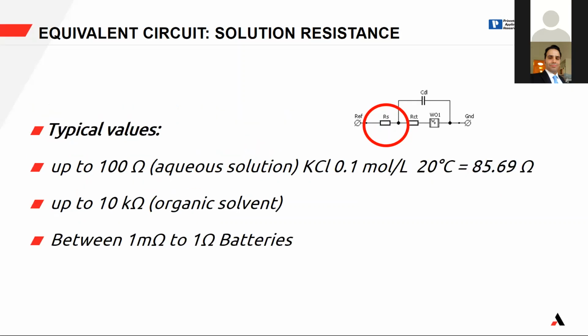The value: normally, if we are in aqueous solution, we are talking about around 100 ohms. I give you a comparison: KCl at 0.1 molar at 20 degrees is 85.69 ohm. So this is used as a standard to check the conductivity. Up to 10 kilo ohm, we have organic solvent. Below 1 milliohm, we have the battery, which is very concentrated salt and very conductive.